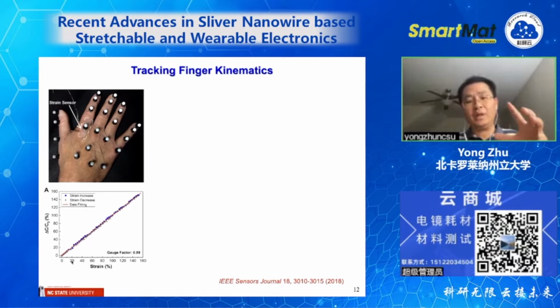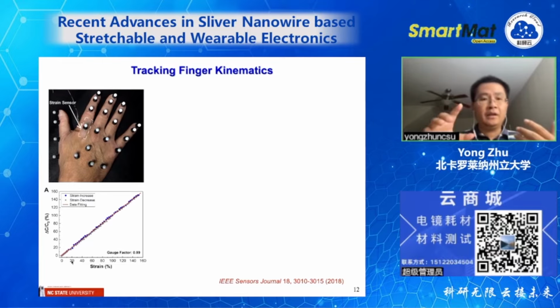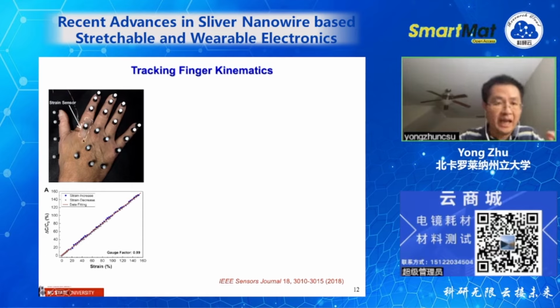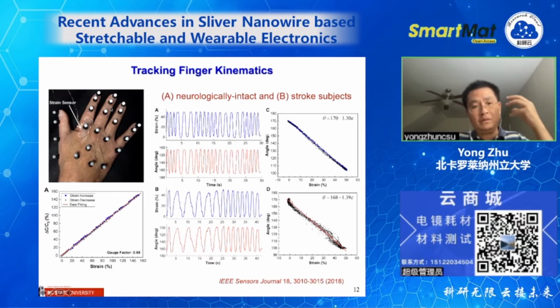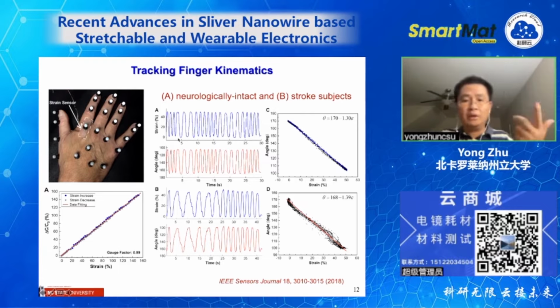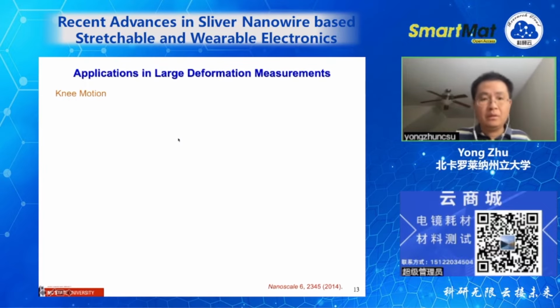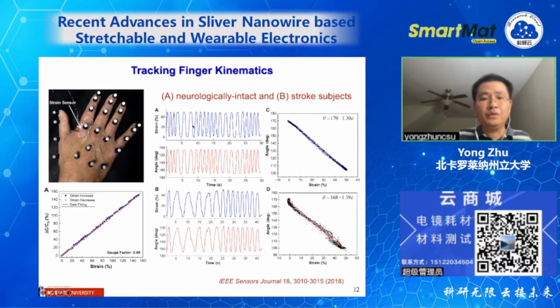For instance, deformation from our joints, like finger knuckles, knees, elbows, where you have large deformation, the strain can be as large as 50% or even more. So in this case, we calibrated our sensor using the gold standard method for deformation measurements. Essentially, you put optical markers on and use multiple cameras. Here, we did this test. The strain, the blue one, comes from our strain sensor, and this angle is coming from this optical method.